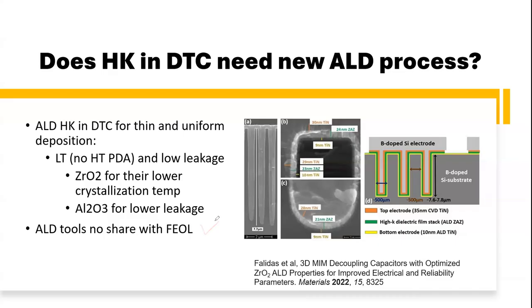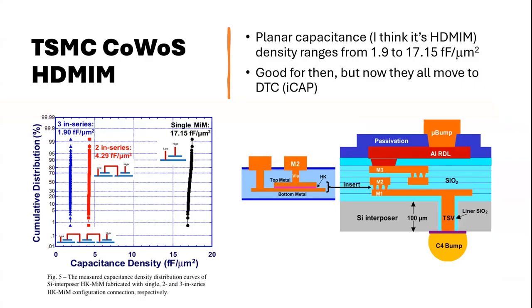So currently you can see that the MIM process technology is going that way. It's playing with hafnium oxide, zirconium oxide, and aluminum oxide with different compositions and different precursors, and trying to improve in a way that you get a little bit higher capacitance, and the reliability issue is still okay. And TSMC, in the early days, had the planar structure, right? It's planar. The highest they can get is 17.